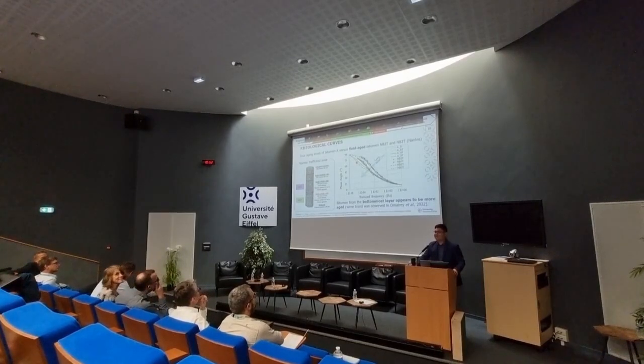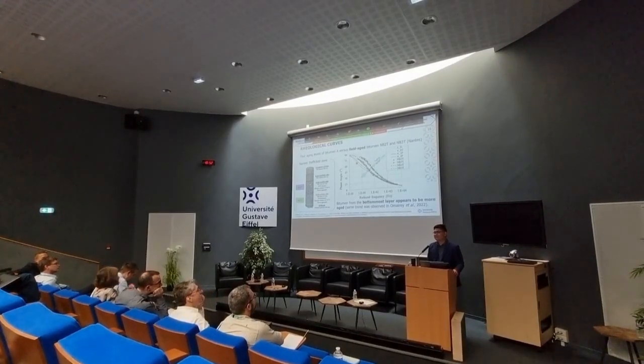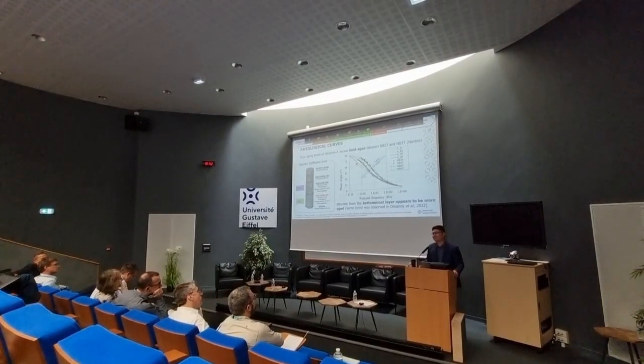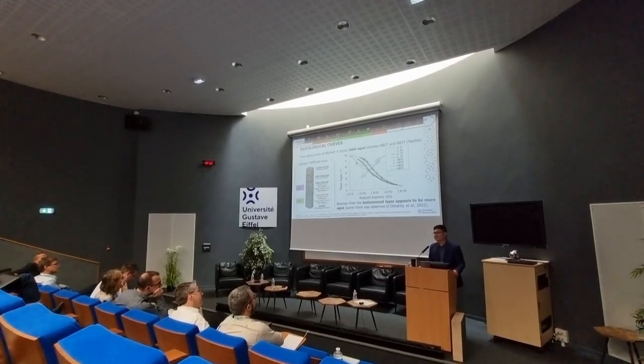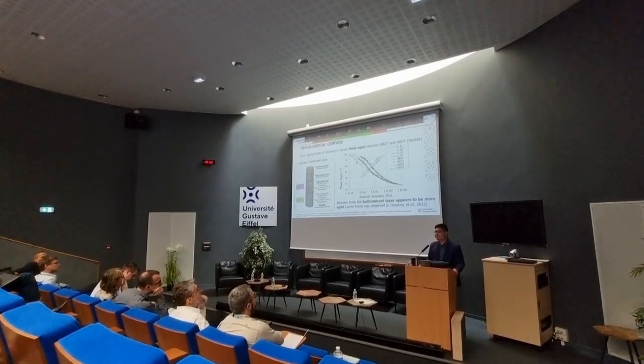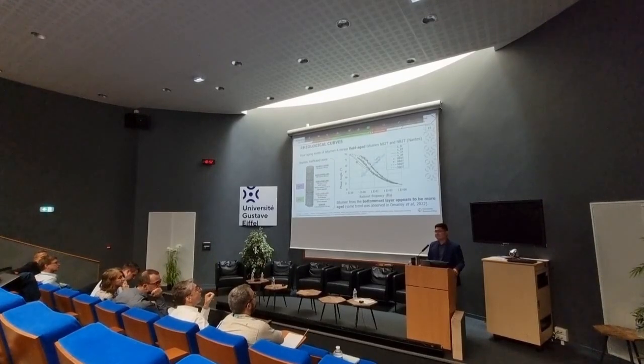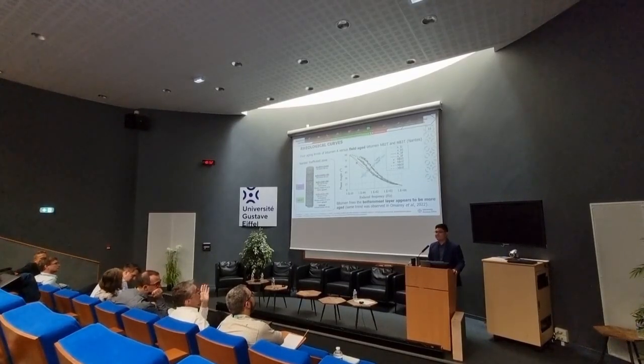You could add a part to your answer, which is the last part of your study, when you correlate TSRST test results with aging. Because TSRST is a test to characterize the cracking at the surface of the pavement due to temperature evolution, of course. And this is a way to damage the pavement. So at least you have correlated the aging of the bitumen with this type of distress. Yes, yes.